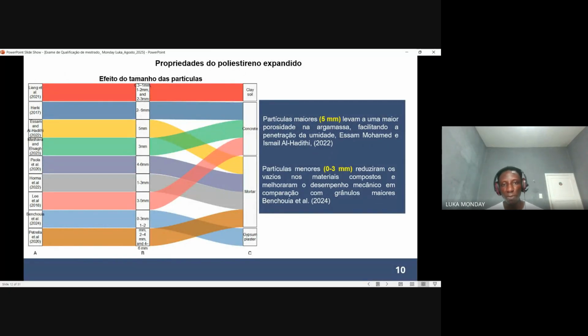On the same vein, particle size also matters with respect to thermal insulation mortar. The bigger the particle size, the more the circulation from the wall within water. So the larger the particle size, the more the circulation and the more the porosity with respect to humidity. While the smaller the particle size, the more the void spaces between these materials tend to be filled. So many authors have explored different particle sizes, while the best particle size is from 0 to 3 millimeters, which is supposed to be used with respect to these materials to minimize the void between these materials.